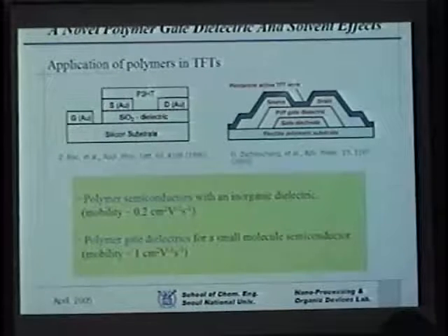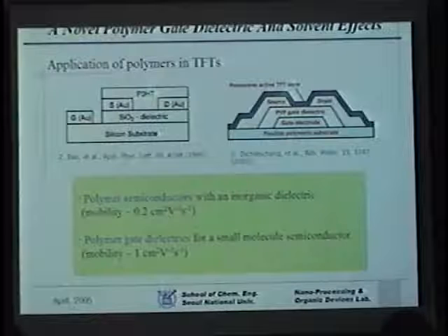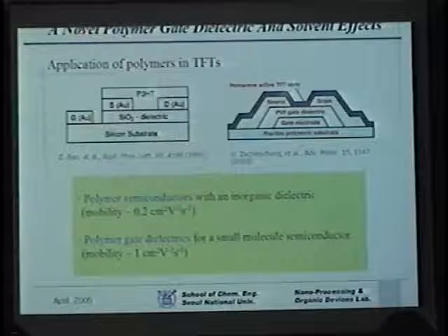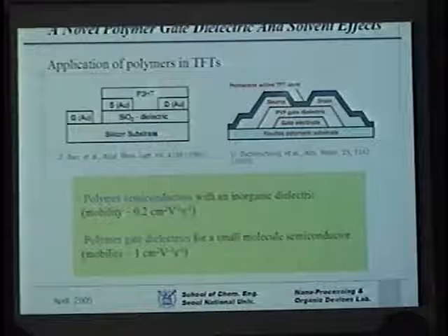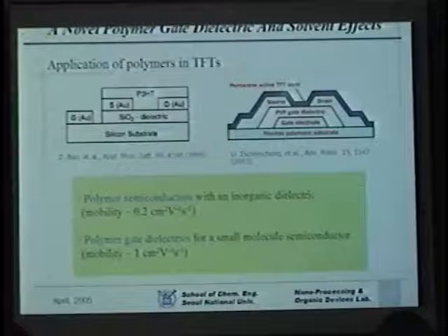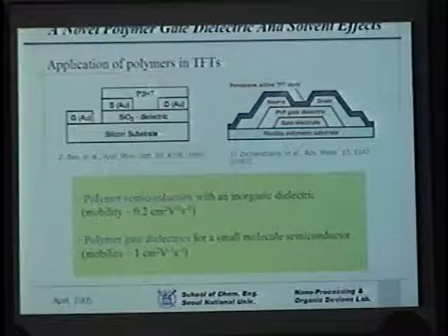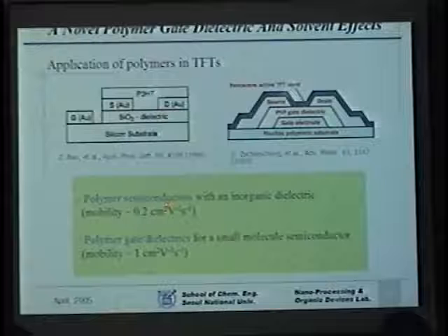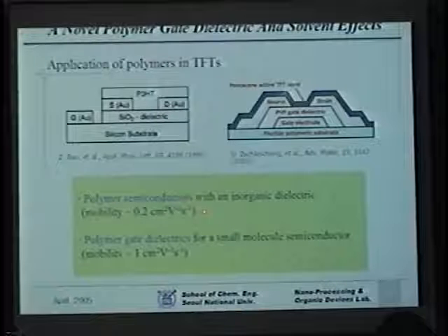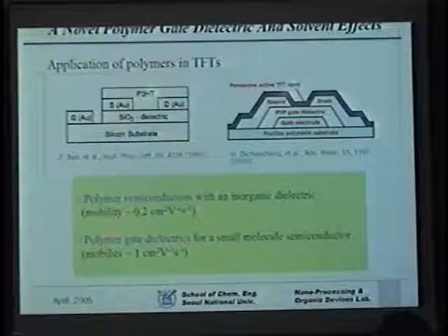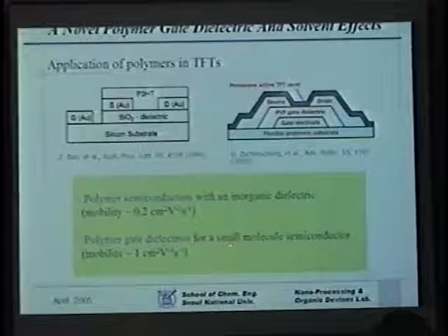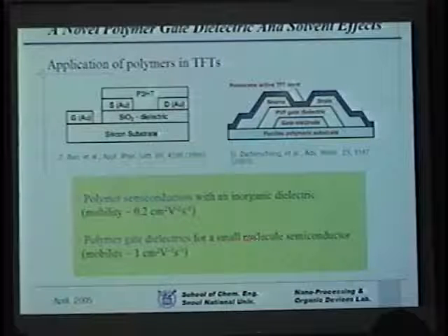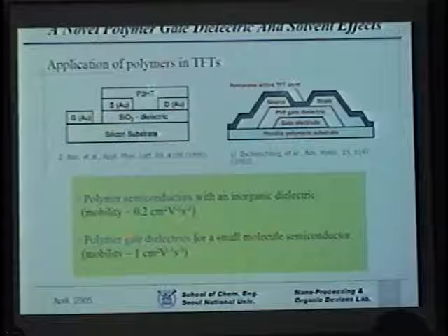In another effort, we tried to come up with, I shouldn't say new, but let me just say a new gate dielectric material. It's known in the literature that with inorganic dielectrics, such as silicon dioxide, and using a polymer semiconductor instead of pentacene, mobility is around 0.2. If you use pentacene and a polymer gate dielectric, it is of the order of 1.